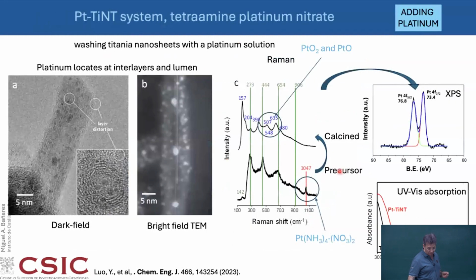And we were doing it with platinum, so that you can get the platinum nanoparticles getting inside the main tube, at the interlayer, or even at the surface. Here, for instance, you have a bright field. So it is preferentially larger ones located in the tube and smaller ones in the interlayer. And the nice thing is that because you get the platinum nanoparticles, and these nanoparticles in the tube get a longer shape, they absorb closer to the visible, and then this photocatalyst can be working not only with UV light, but also with visible light.